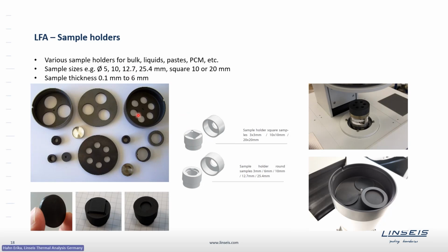The equipped sample carrier is then placed into the instrument. Here you can see an open one. This is the carrier for 3 samples. In the middle, we have the sample thermocouple measuring the sample temperature. It is very close to the sample and at the same height as the sample, so that we have a precise measurement of sample temperature without the need to contact the sample. The thermocouple has a fixed position. We also close this sample holder as we want to guarantee a homogeneous temperature stabilization within the instrument, within the furnace, as well as within this sample carrier. Here you can see a closed one, and how it is placed in the system.